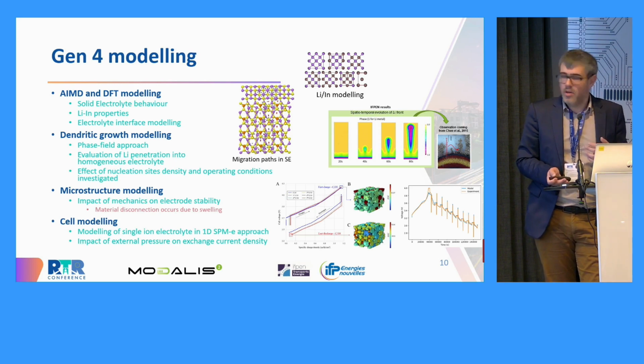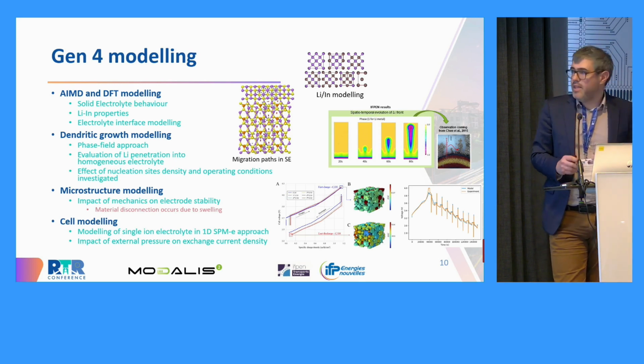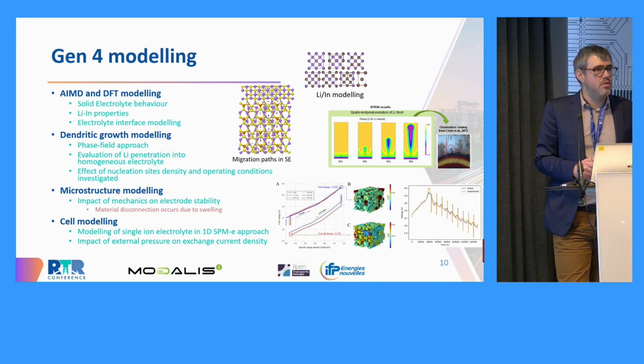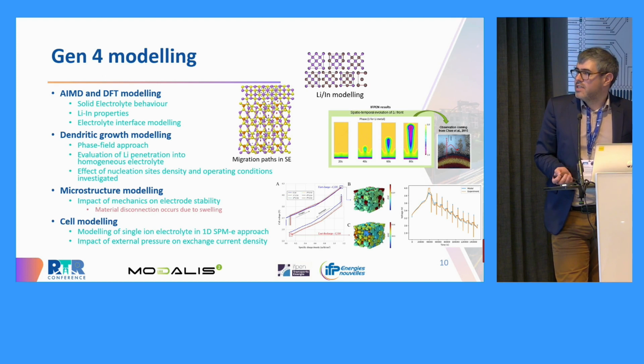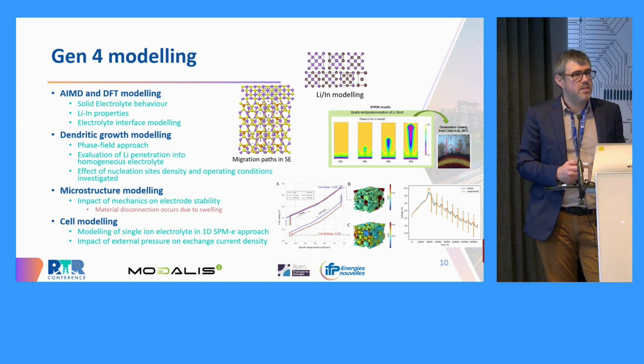We went to microstructure modeling in order to evaluate the effect of the microstructure on the positive electrode behavior with the NMC. It showed that due to swelling of the NMC and mechanical stress, we had a very fast degradation of the interfaces at the NMC side, leading to material capacity fade for the cells. And finally, at the full cell level, we were able to validate the model behavior in 1D on the full cell behavior in order to finalize this model at the end of the project.